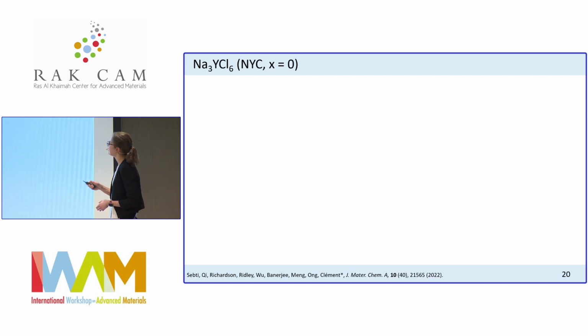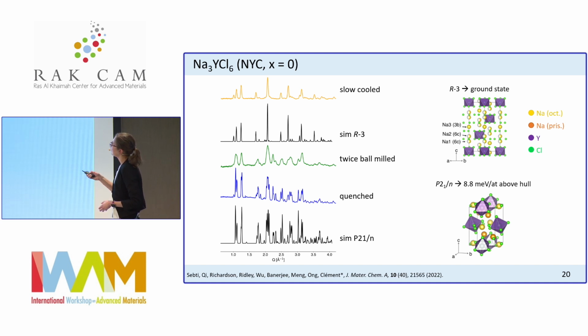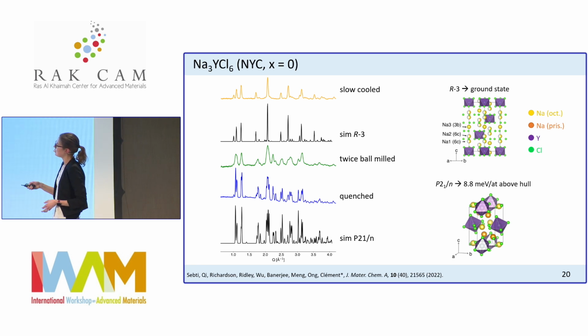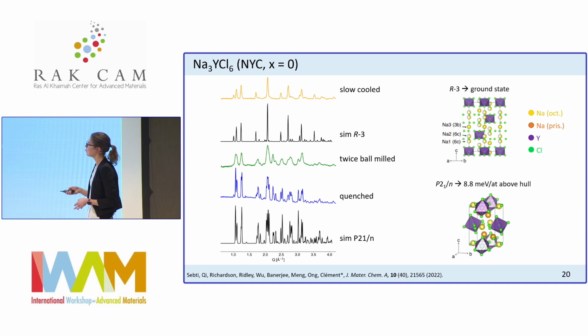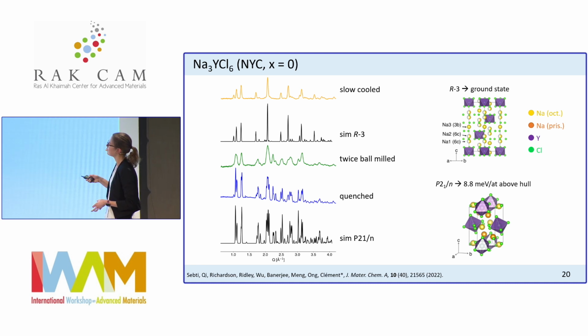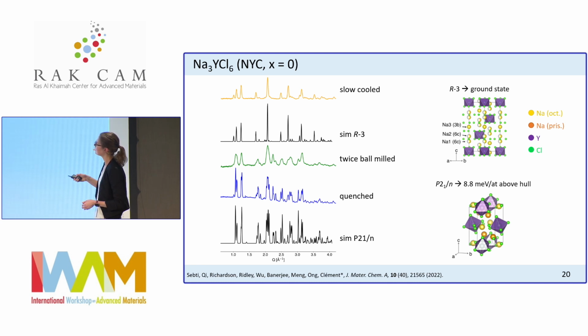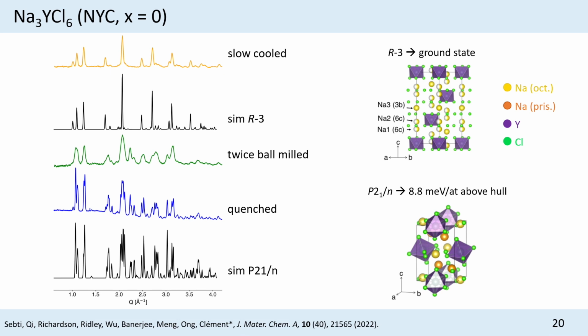So now looking at the other member, NYC, here again we did a slow cooling process, twice ball milled and quenched. So the 3 patterns that we get are shown here. The problem is that these patterns, especially those ones, are very difficult to fit with Rietveld refinements, so we decided to simply compare them to the simulated spectra we would get for the 2 polymorphs of NYC that had been reported in the literature. R-bar-3 is one of the structures, and the other structure is the monoclinic P21/n. If you compare the simulated spectrum for the R-bar-3 structure, it's very similar to the slow-cooled pattern, suggesting that the slow-cooled sample is mostly this R-bar-3 ground state structure that we find with DFT.